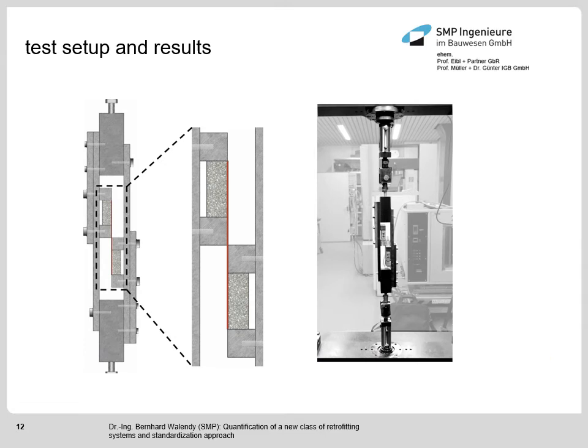This is the most important test setup which has been used for the quantification of the seismic wallpaper. It is a single shear test with very short anchorage lengths, and this test setup was pretty easy to install, and many tests could be conducted in order to quantify the effects of testing speed, different carrier substrates, or the effect of air humidity or temperature. And if you are interested in the details of this test setup and why it is possible with it to directly determine the so-called bond-slip relations, I recommend to have a look at my PhD thesis.